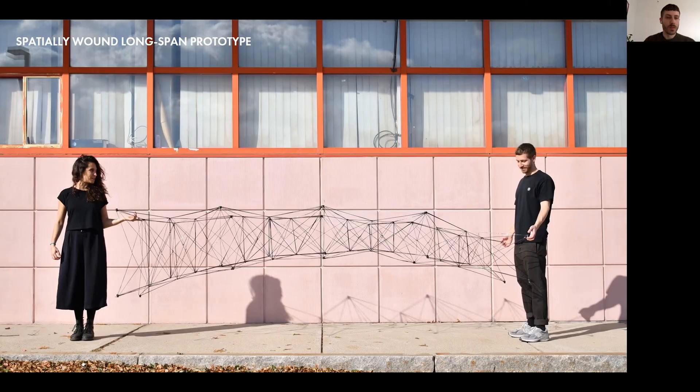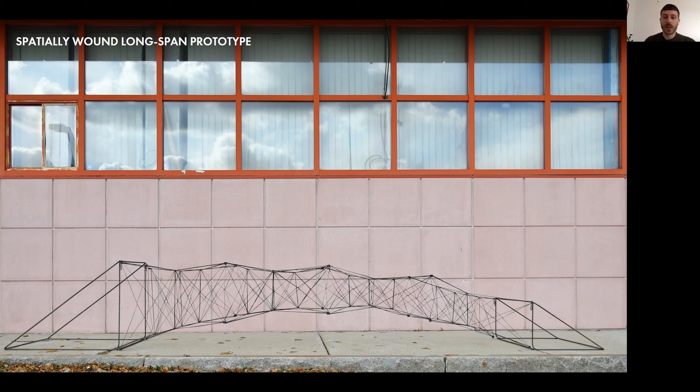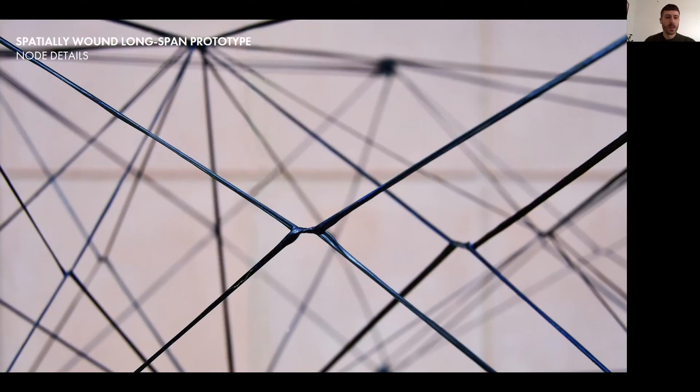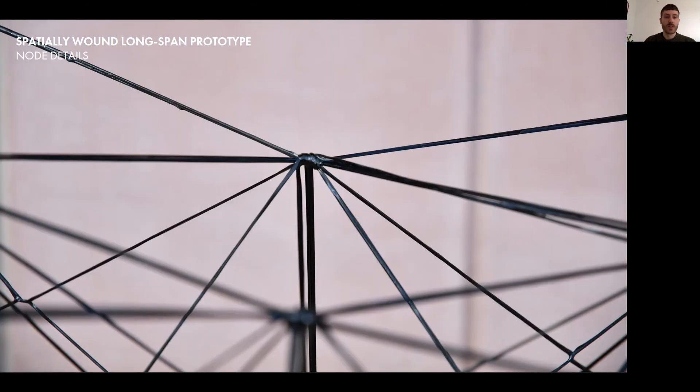Here are some impressions from the final demonstrator. For this prototype, we opted for industrially-made prepregs which were dry to the touch and could be handled at room temperature without curing, so much more suitable for the robotic fabrication process. However, the dryness of the fibers actually turned out to be an issue because it prevented them from sliding properly, which meant that we had to manually adjust the node positions, and the final structure was therefore also wound by hand.